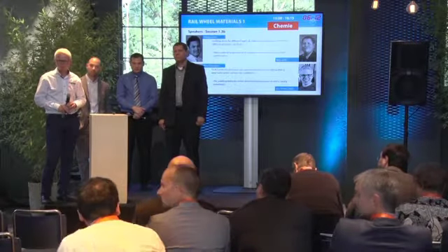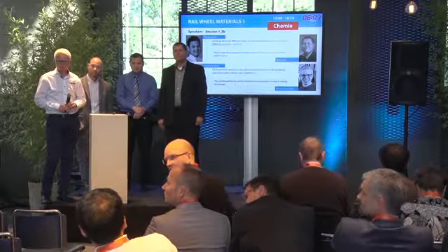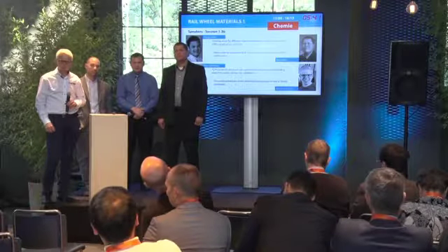May I continue this discussion? So, as I said, you did a very good work. My concern is plastic deformation is load path dependent, load history dependent. Therefore, if you have a single loading to reach a high plastic deformation, it might be different for the material behavior from small plastic deformation accumulating until it reaches this large deformation. So that's my concern.